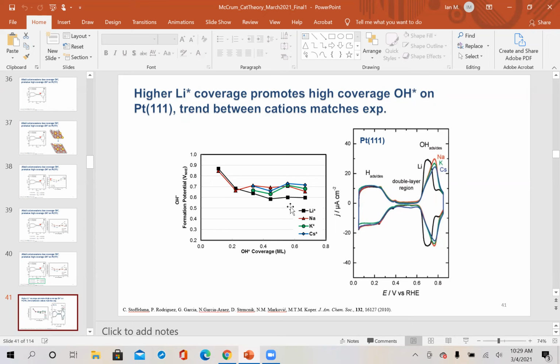I guess my last point is also, the electrosorption valencies of these cations are also different, right? Yes. And so we could then also say, beyond the charge of the ion in solution, if they do transfer some small portion of an electron with the surface, maybe they take different charges on the surface. Yeah. We've also looked at that. The degree of charge transfer is small. Yeah. 0.1 of an electron, something on that order. If we add more solvation, that also decreases a bit. Yeah. But it is different.